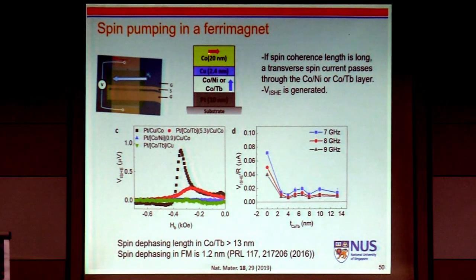That means this spin is immediately dephased by about 1 nanometer of ferromagnet, which is well known. The typical spin dephasing length in a ferromagnet is about 1 nanometer. But in the case of the ferrimagnet, even with 5.3 nanometer ferrimagnet, we can see a clear spin pumping signal, and we indeed studied it as a function of this cobalt terbium thickness, and we were able to see the signal all the way up to 13 nanometer. And we stopped here because we never expected the spin signal to survive up to this.